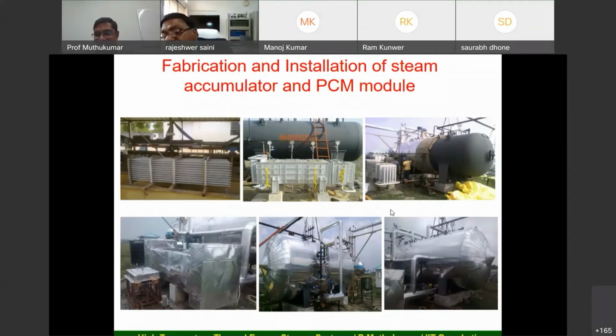So many parameters. Another question is, what are the challenges associated with direct steam generation via single pass using PCM based thermal storage? We also explored this kind of steam accumulator. Initially, we thought of keeping the PCM cartridge inside the steam accumulator itself. Later we went through several exercises, because with a salt based PCM, which is highly corrosive, if any puncture happens, everything will get mixed inside the system. So there is a danger. Here the process and technique are okay, but the question is how strong your heat exchanger material is, and how you ensure there is no corrosion with your PCM.